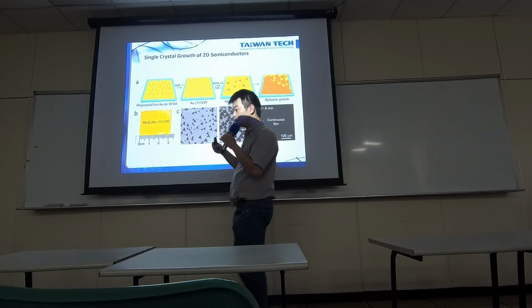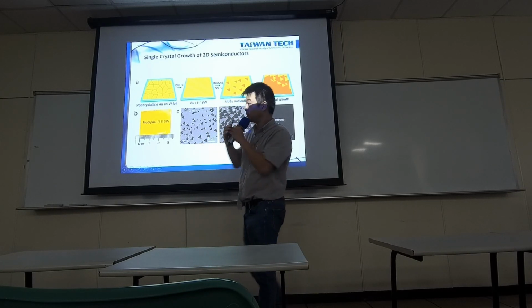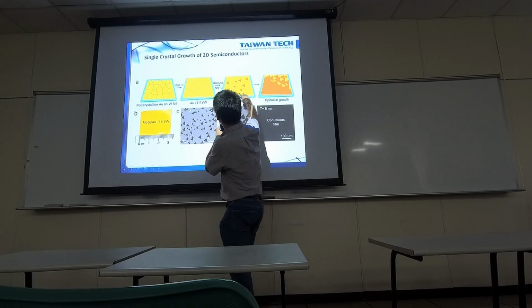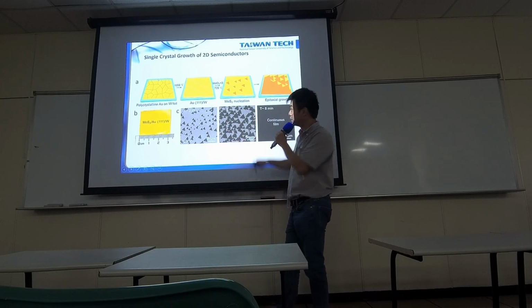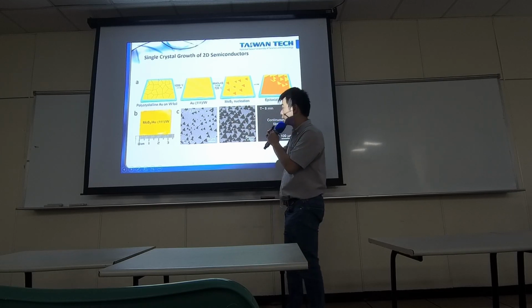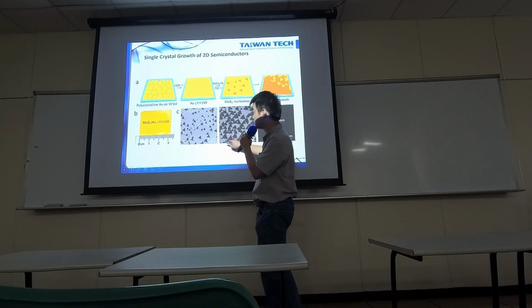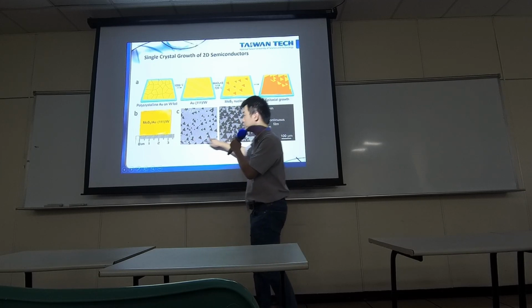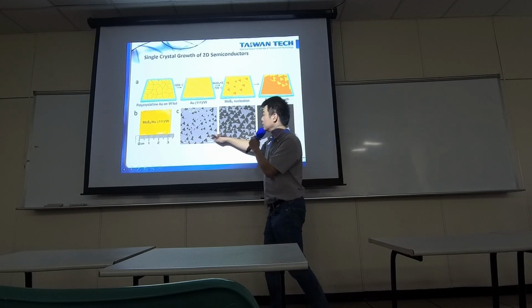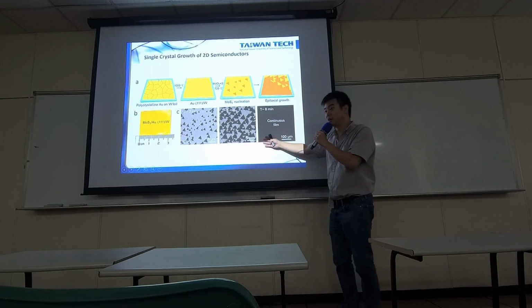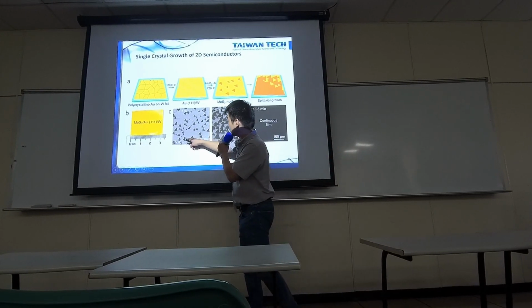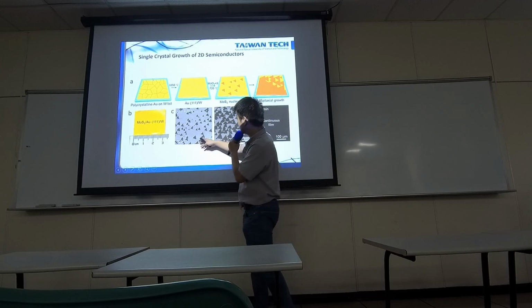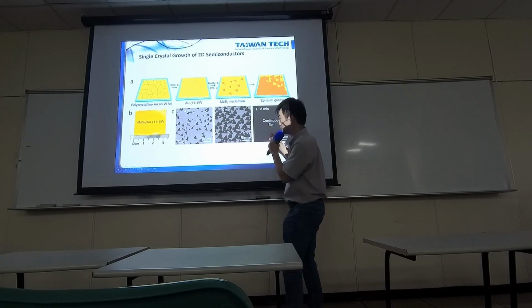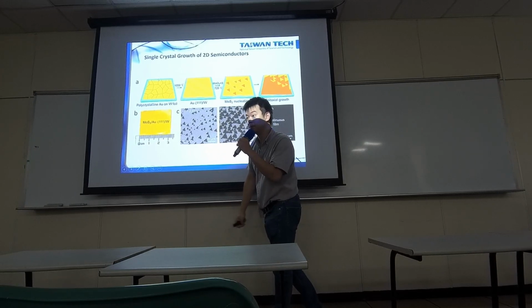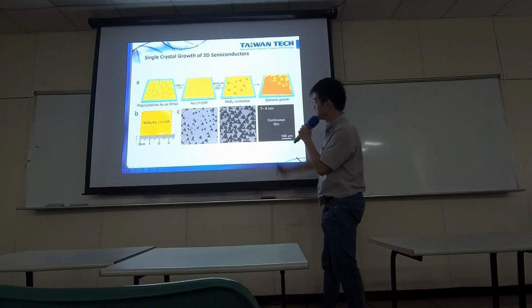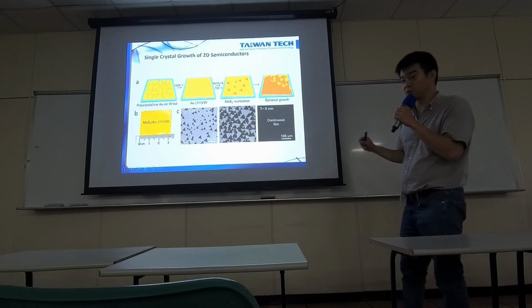And due to the lattice match between your substrate and your MoS2, it tends to arrange in the same direction, right? You see these crystals all arranged in the same direction. By controlling the time, you will be growing into the film. So if it's grown along the same direction, then when it grows to a film, there will be no boundary between them. So this is quite critical. It's not very easy to achieve.